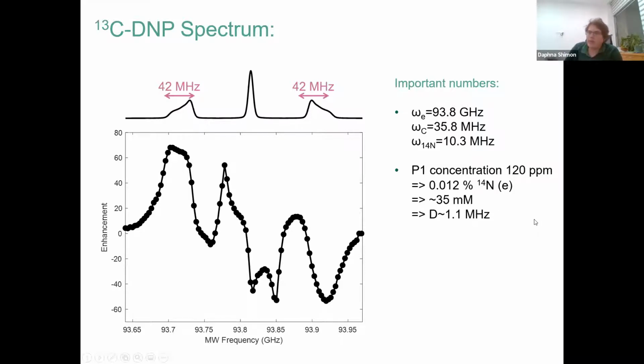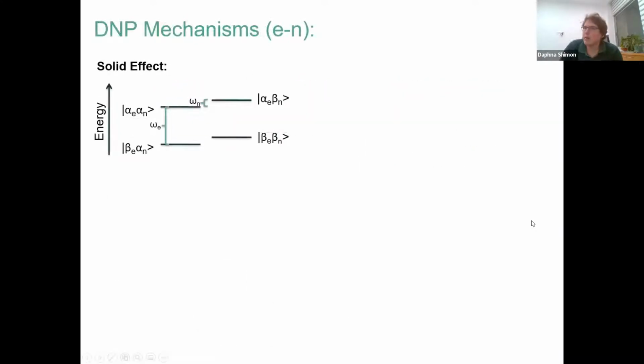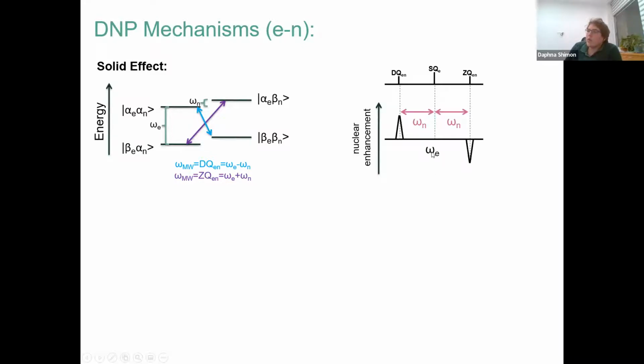So we're going to think about the solid effect and the Overhauser effect and the cross effect. If we're going to think about the mechanisms, we need to decide what we expect the mechanisms to look like in our sample. So if we look at an electron coupled to a nucleus, we can see the solid effect in this type of system if we irradiate on a double quantum or a zero quantum transition, so a transition that involves an electron and the nucleus both changing spin states together, then we can get DNP enhancement. And so if we irradiate at the electron frequency omega E minus omega N, we get positive enhancement. And if we irradiate at omega E plus omega N, we get negative enhancement. So that's what we expect for each EPR line.